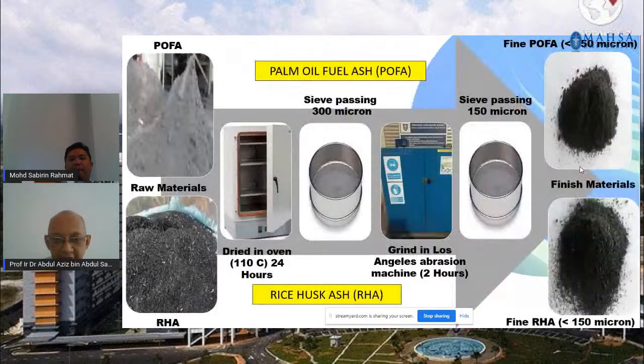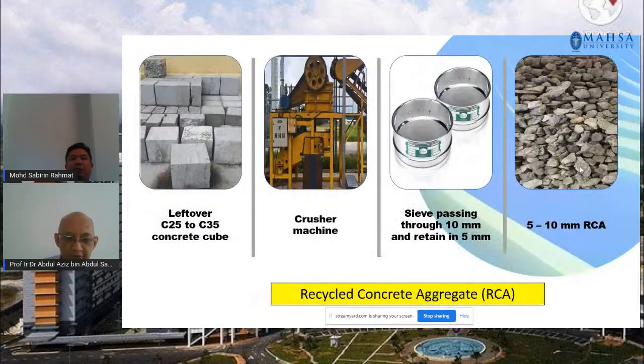I'll just show you again. To get this palm oil fuel ash and the rice-husk ash, we have to dry them, grind them, sieve them. And then we have to make sure that we have enough materials for our mix. The same goes for the recycled concrete aggregate, where we have to crush them, sieve them, and make sure that we get the right sizes that we are looking for.